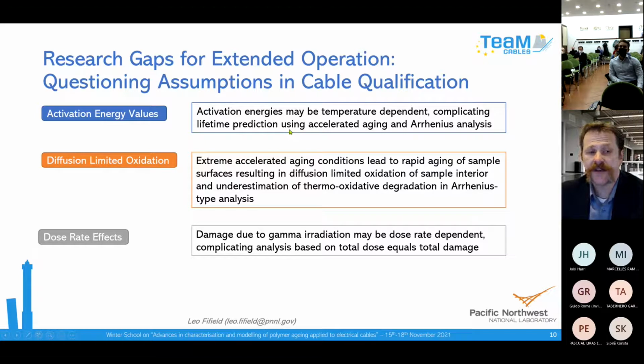But the question is that the activation energy that you determine through a series of elevated temperatures might actually be temperature dependent. The aging behavior of a cable in a plant over decades at, say, 40 or 50 C, or a lower temperature, might be different than what happens in the laboratory when you're doing 165 C accelerated aging. That's a complication because it's hard to do a 40-year experiment to see how the cable is operating, or even a 10-year experiment. When you're limited to months or maybe a year or two on an experiment, you have to do some extreme accelerated aging, and the activation energy may not be the same in those different conditions.